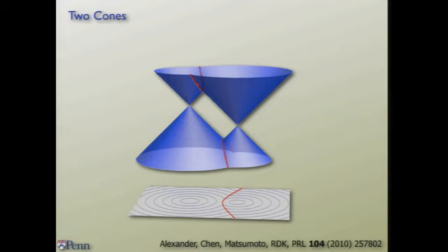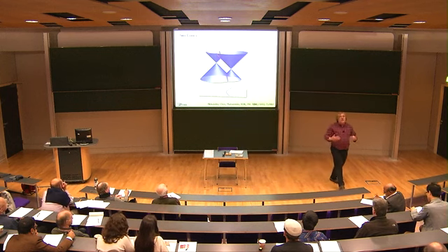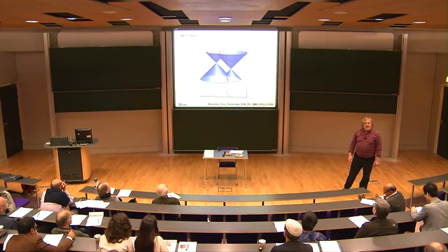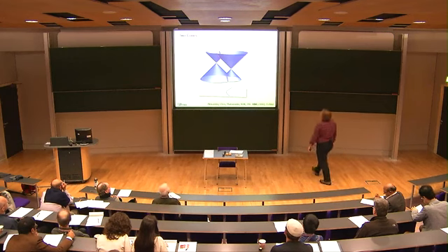Look at that. When two sets of circles crash into each other, they crash into each other on a hyperbola, which is sometimes a straight line. All right? But we understand this completely. To have equally spaced two-dimensional surfaces, I need to have pieces of cone, right? I already showed you that. They have to be pieces of cone. Now I can have different pieces of cone intersecting, and because they have the same slope, when two pieces of cone with the same slope intersect, they always intersect on conic sections. Because they intersect on a plane, and when a plane cuts a cone, you get a conic section. So they always are conic sections. In two dimensions, they have to be pieces of conic sections.